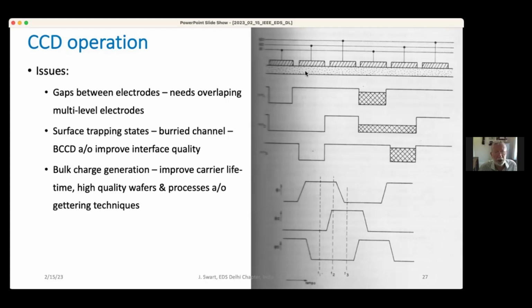So one issue is the gap between electrodes, which makes this not ideal. There will be some potential bump here, so that not all the charge will be transferred, reducing efficiency. Also, you can have surface states that trap part of the charge, which also reduces efficiency. The first one can be solved by overlapping, using gates that are overlapped one on the other, and the charge trapping can be reduced by using a buried layer. So then it will not be a surface CCD, but a buried channel.